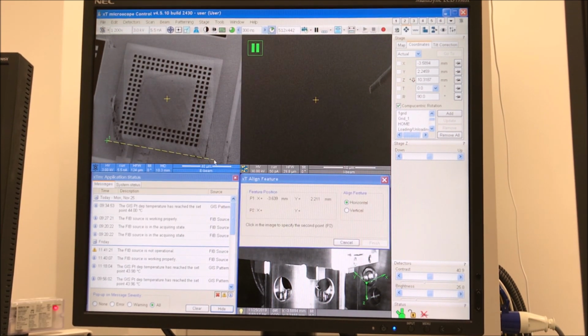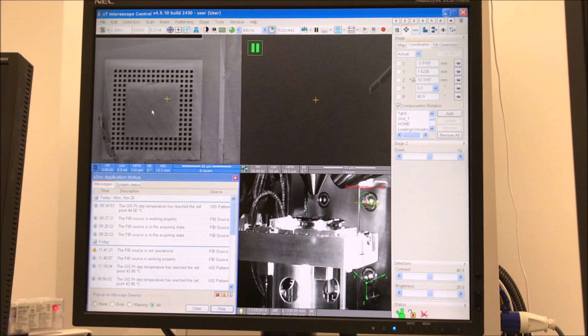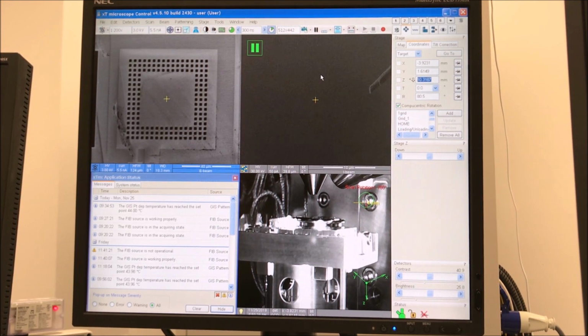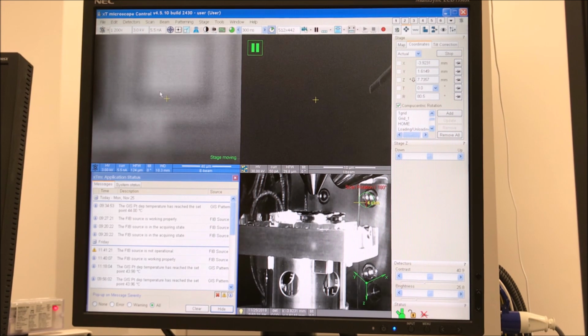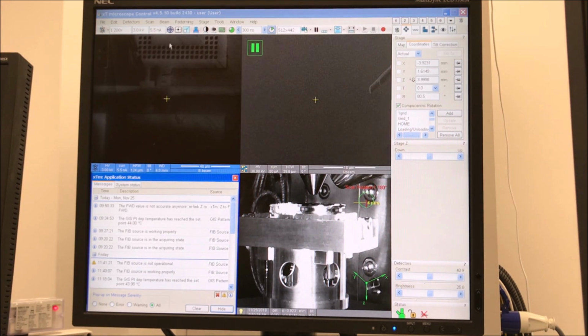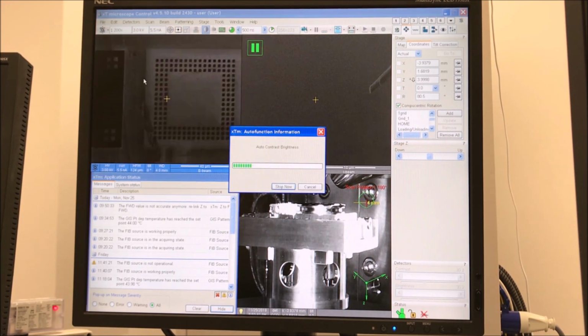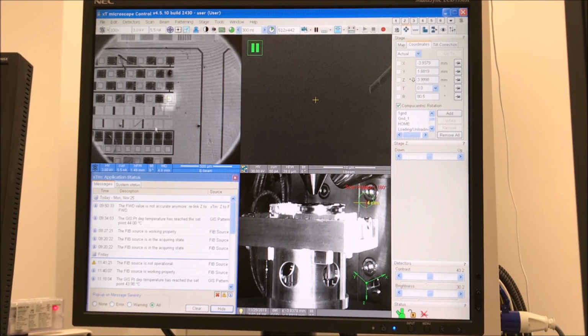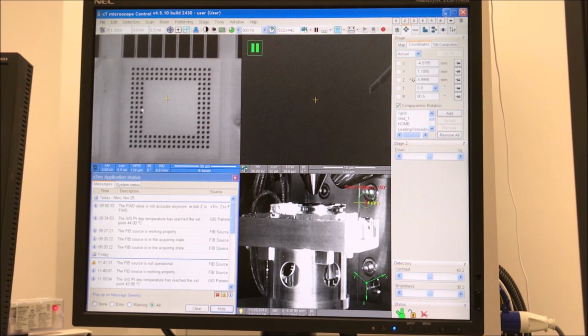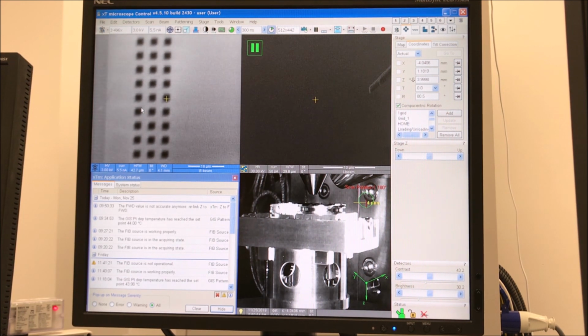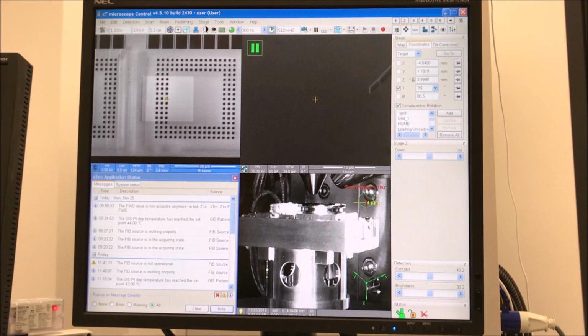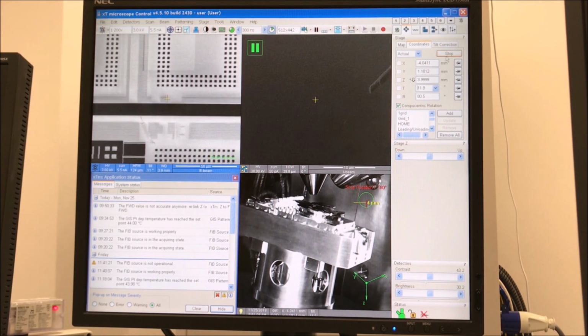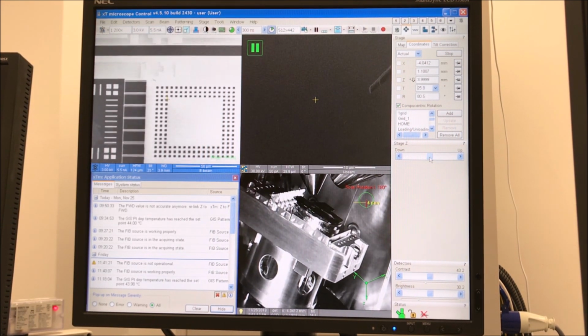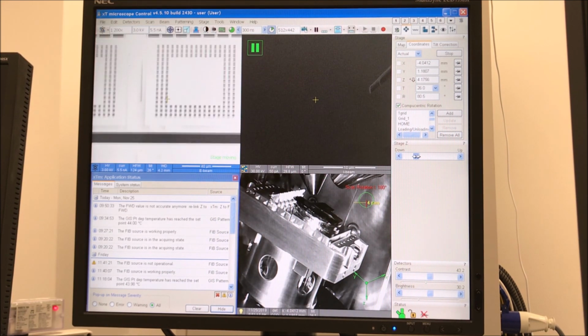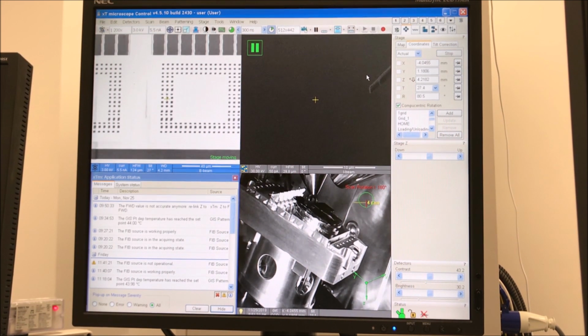I'm going to align the pad so those features are square in the image, because those are actually cleave directions for the substrate that I want to use for imaging when I prepare the lamella and eventually put it into the TEM. So now I'm setting eccentric height. I focused and linked the working distance, and now I'm tilting. I see the image shift from the middle, my feature of interest rather. Then I'm using the Z control of the stage to bring it back.